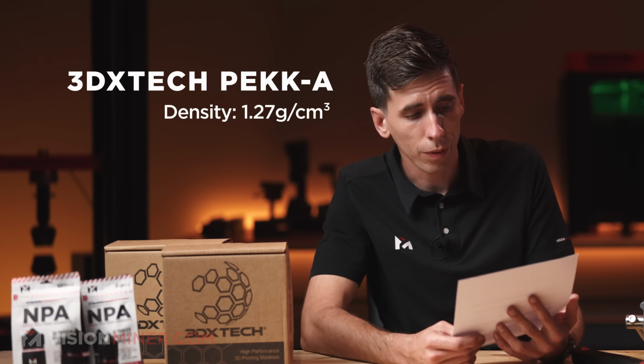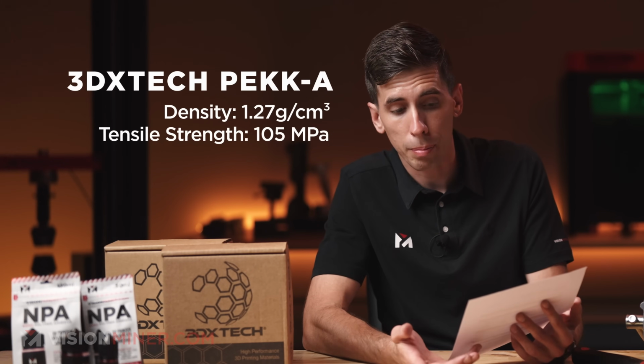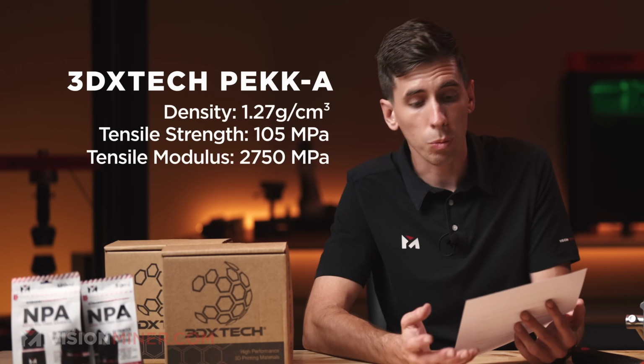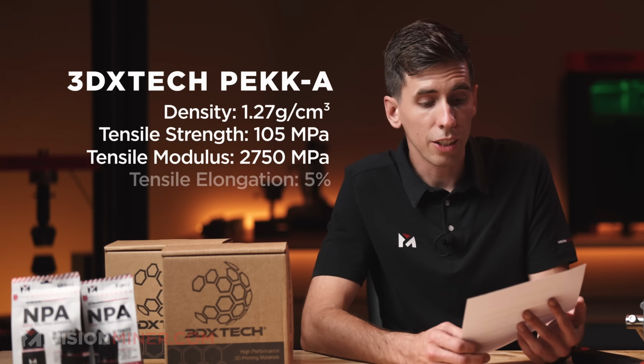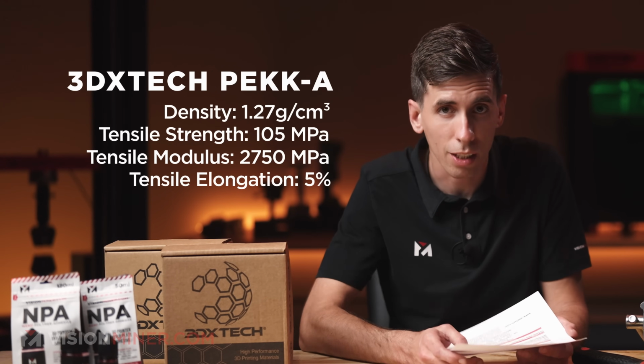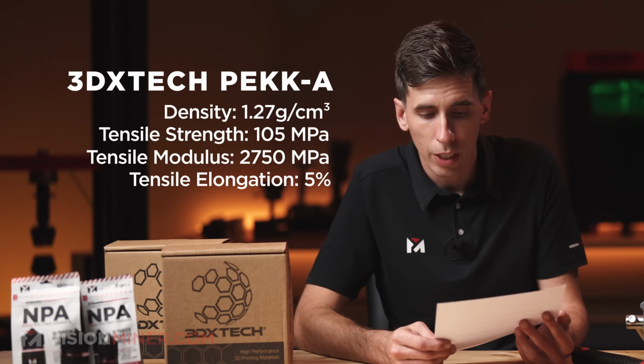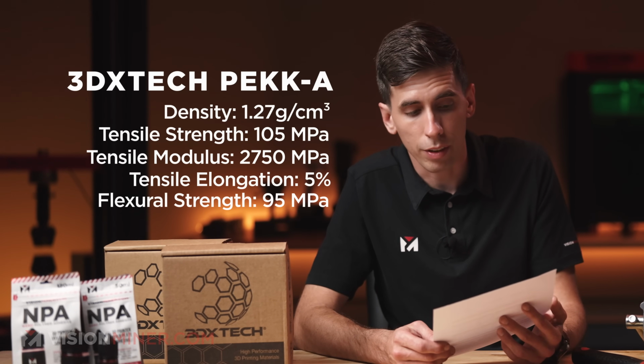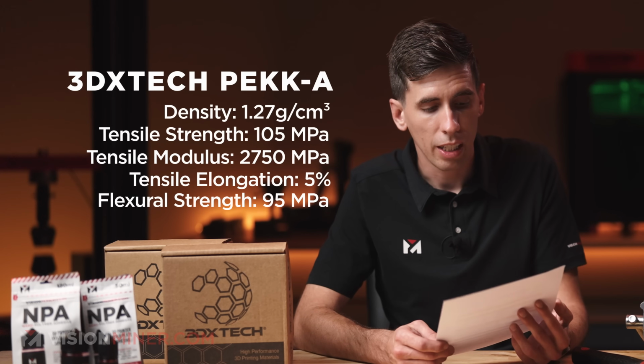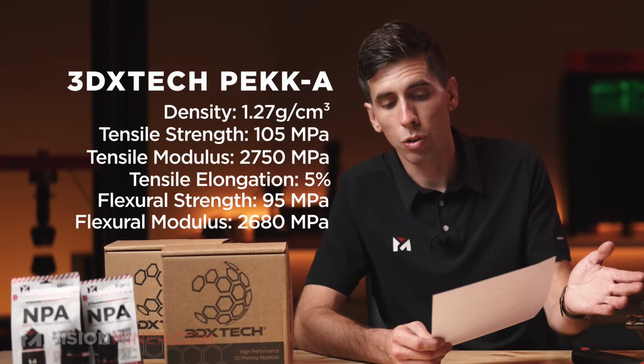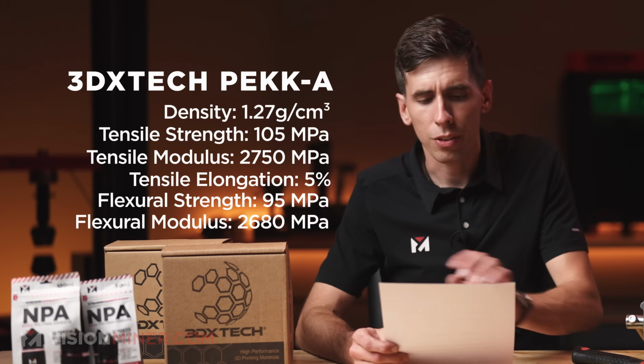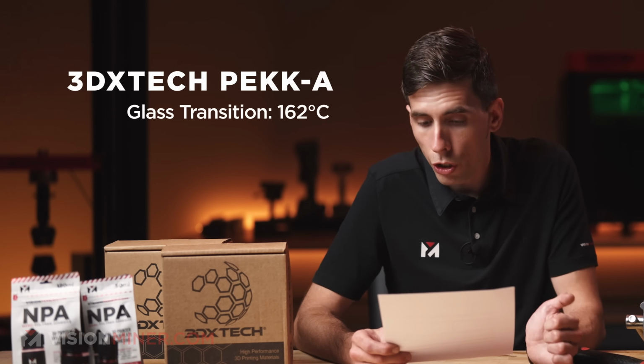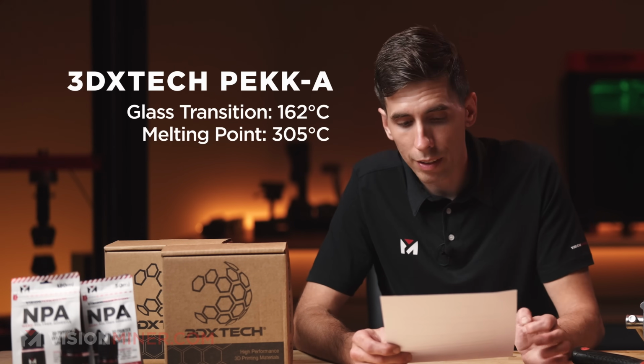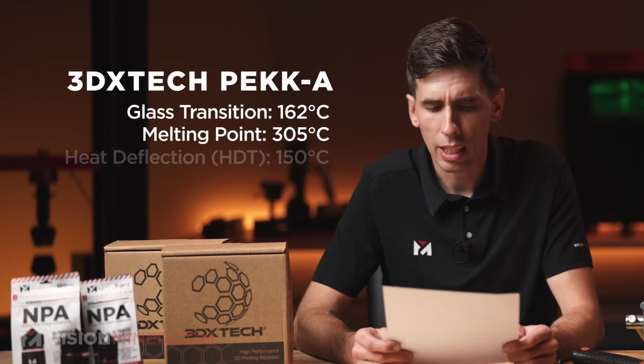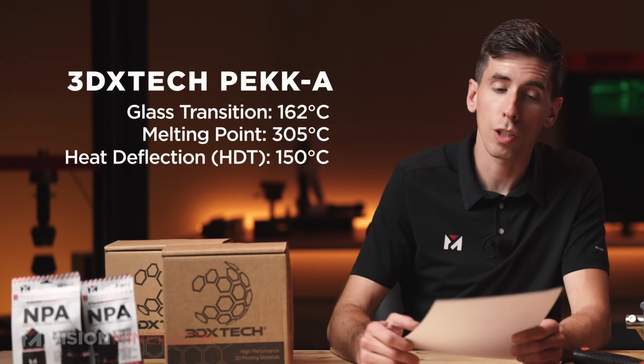We've got a density of 1.27 grams per cubic centimeter, tensile strength of 105 megapascals, tensile modulus of 2750 MPa, tensile elongation of 5%. I'll show that here in a second, hopefully. And flexural strength of 95 megapascals, and flexural modulus of 2,680 megapascals. The glass transition temperature is 162. The melt temperature is 305. These are all Celsius.